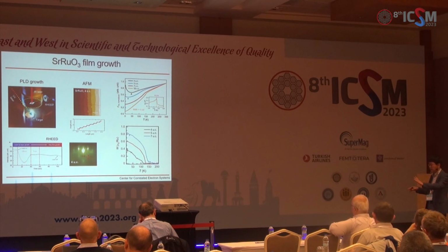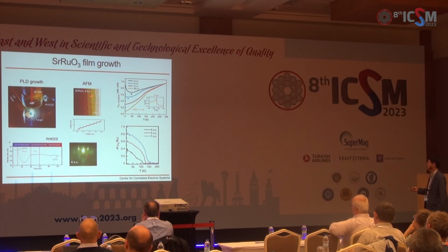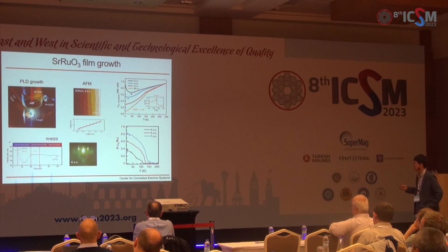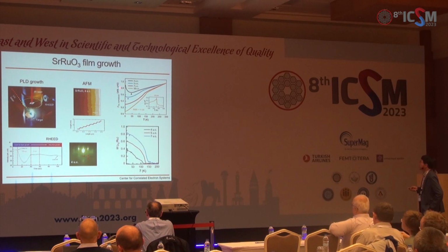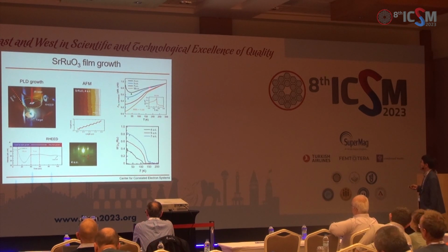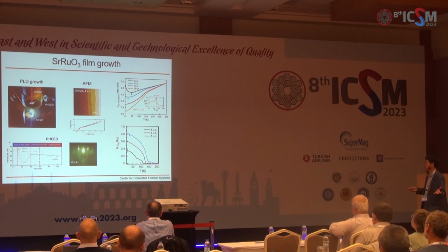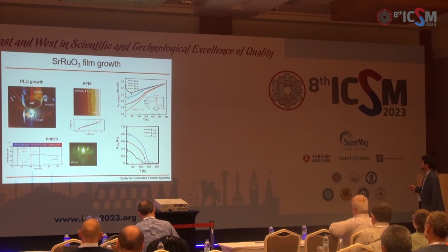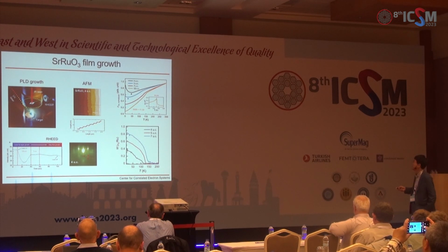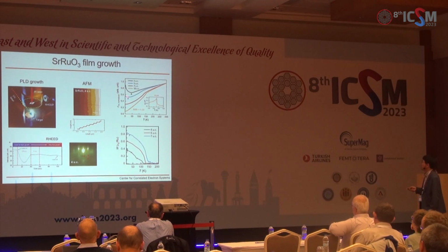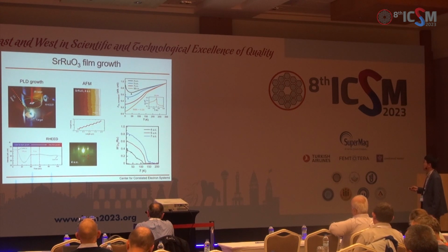So it grows along terraces, and you can see that the terraces of the substrate can be seen very nicely, with very nice steps. The RHEED pattern shows oscillation initially, but it flattens because it grows in step-terrace mode. If we measure longitudinal resistivity as a function of temperature for thick films, this resistivity looks more like bulk, with a kink at high temperature and more or less a Fermi-liquid-like behavior with a fairly high residual resistivity ratio. But as we reduce the thickness down to 4 unit cell, at very low temperature it shows insulating behavior.